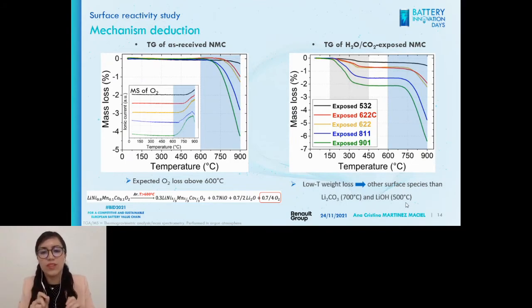Then the exposed materials were very interesting because they present this huge weight loss above 600 degrees, but they also present a weight loss in the range of 150 to 450 degrees Celsius, which does not correspond to the decomposition of carbonates, because that occurs at 700 degrees, and also does not correspond to the decomposition of hydroxides, because that occurs at 500 degrees. So what is going on in this temperature range?